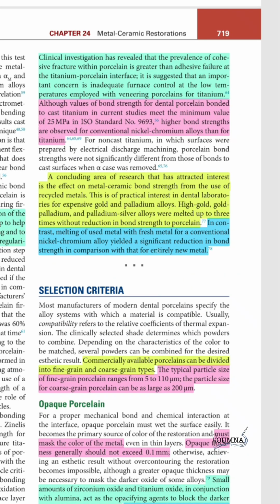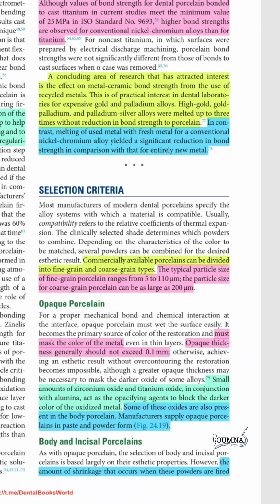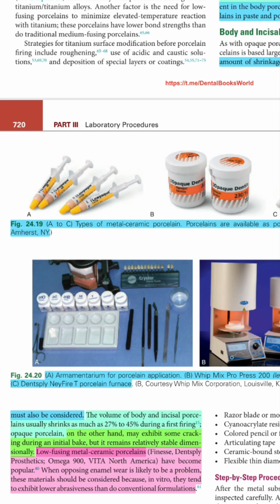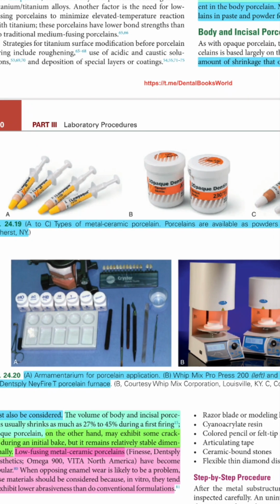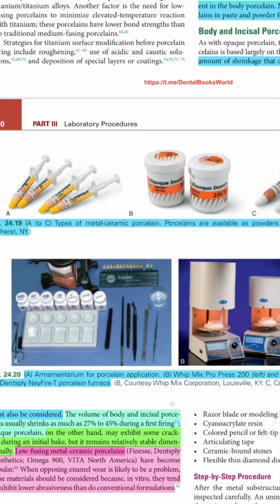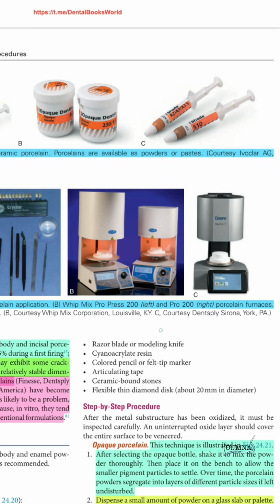Another research about the recycling of expensive gold and palladium alloys has found that it did not reduce the bond strength to porcelain. On the contrary, using a recycled conventional nickel chromium has a significant reduction in the bond strength of the alloys. These are the types of the metal ceramic porcelain. They can be powders or pastes. These are the porcelain furnaces.